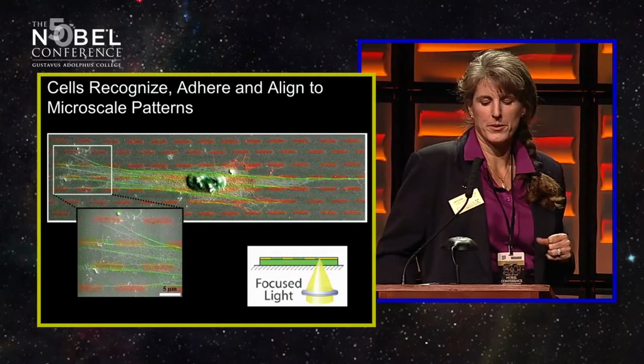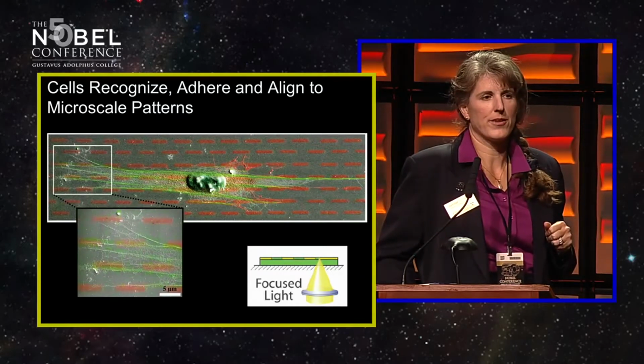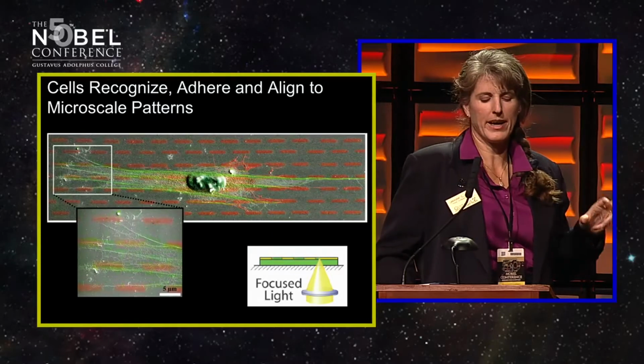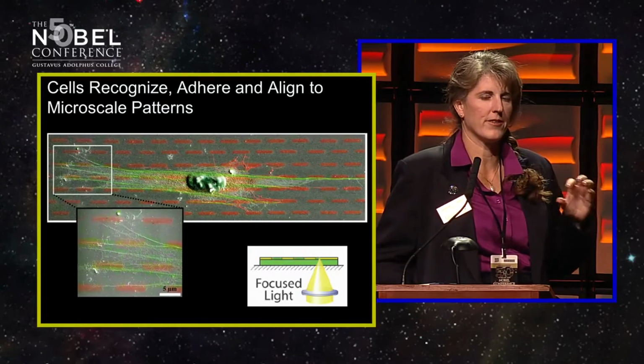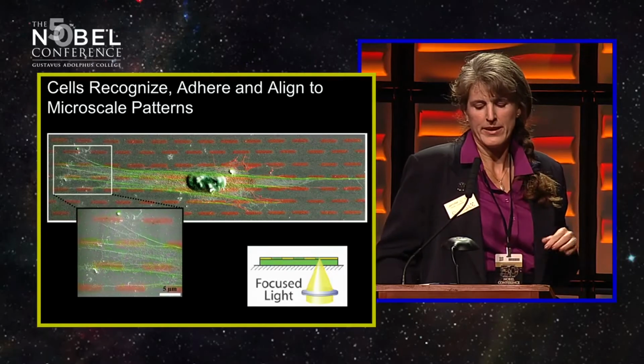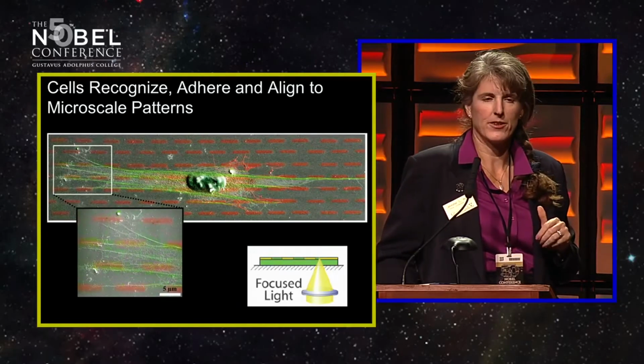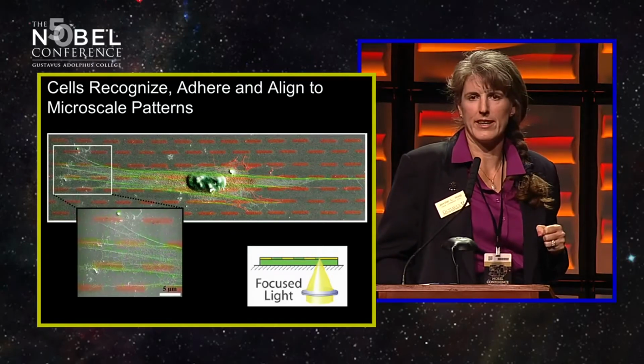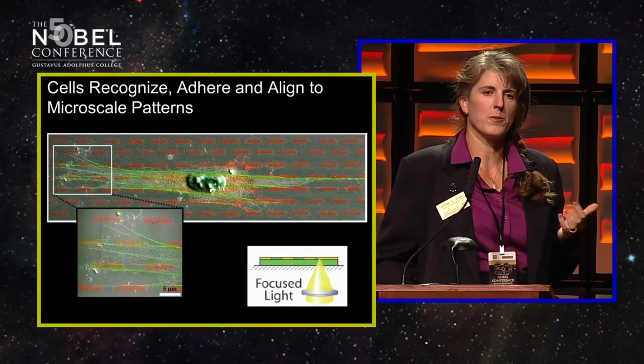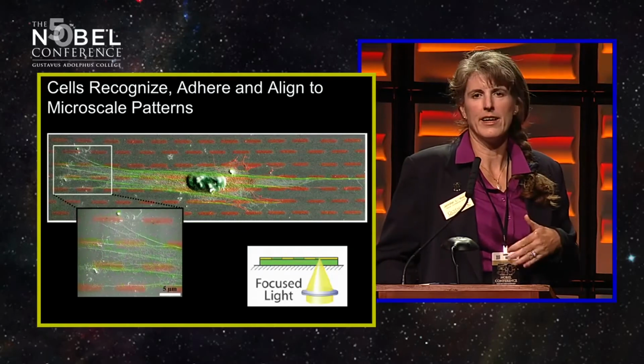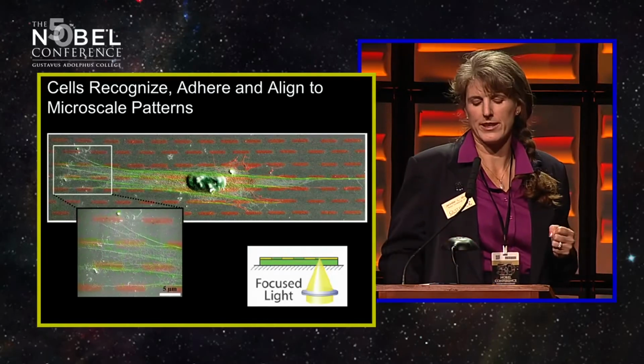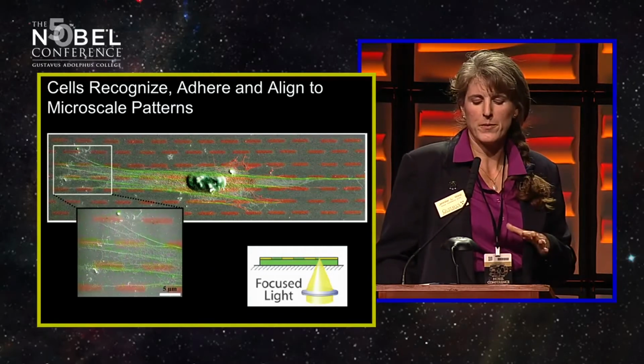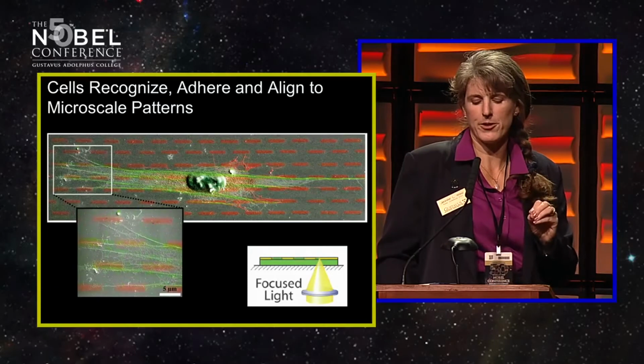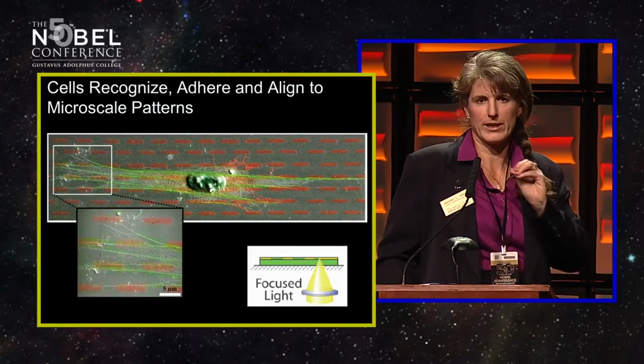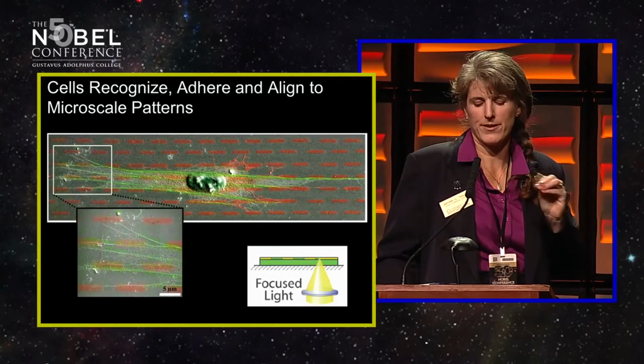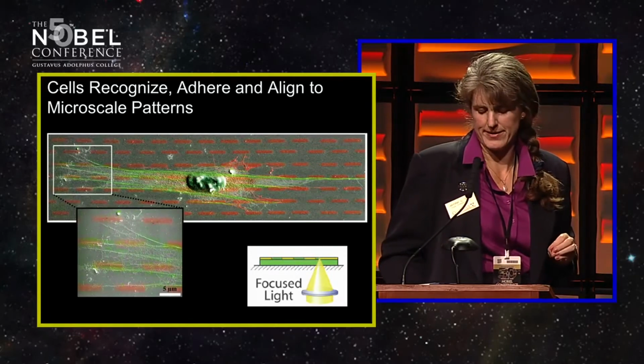So this is an example looking at a cell grown on the surface of a hydrogel where we were presenting patterns, which are kind of the orangish-red dots you see. The cell has its actin fibers stained in green, and you can see that the cell and its actin fibers have aligned in the direction of the patterned ellipses. So just how we presented this to the cell had a profound influence on how the cell organized and interacted with this material. These patterns were formed by using highly focused laser light to control where we allowed photochemistry to occur when we were cross-linking in the ligands that would bind to the cell surface receptors.